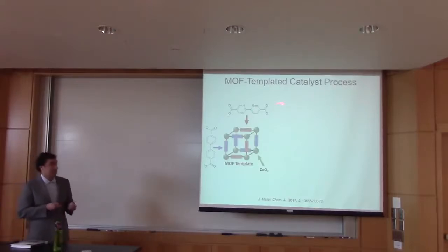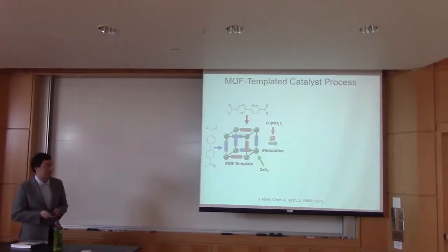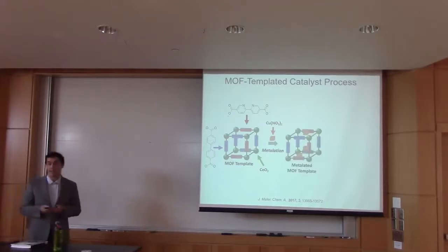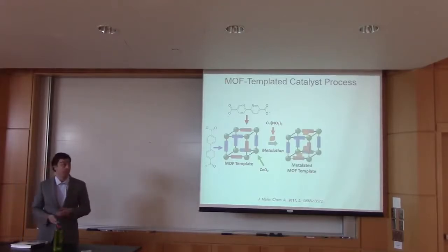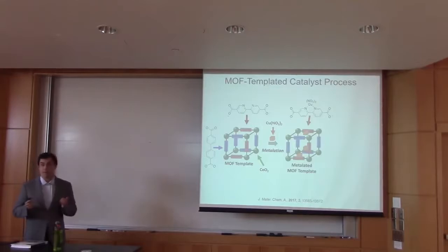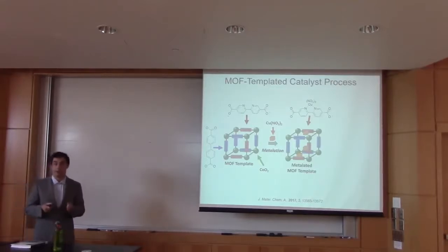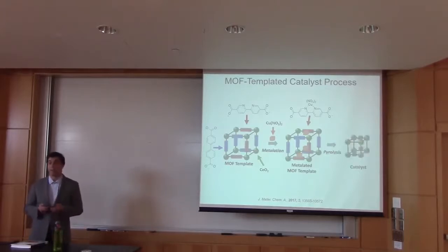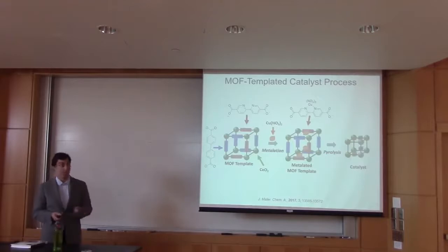The next thing that this bipyridine ligand will allow us to do is introduce a secondary metal, this copper(II) salt, and this orange cube, as it's represented by, which can now be incorporated kind of uniformly throughout our framework. And it'll be grabbed on by those nitrogens in that bipyridine linker and kind of held in place in that MOF. From here, we're going to pyrolyze and remove all the organic units using high temperature to decompose the MOF and be left with just metal oxides.